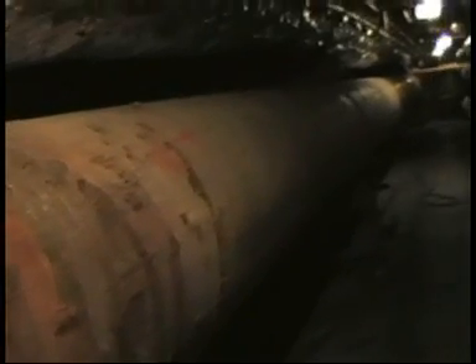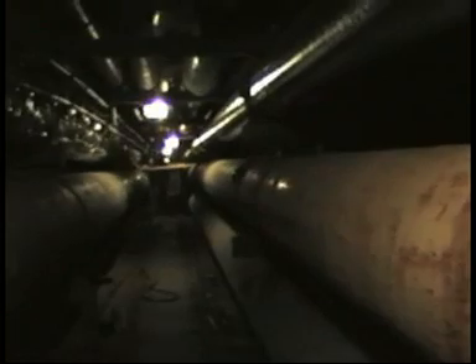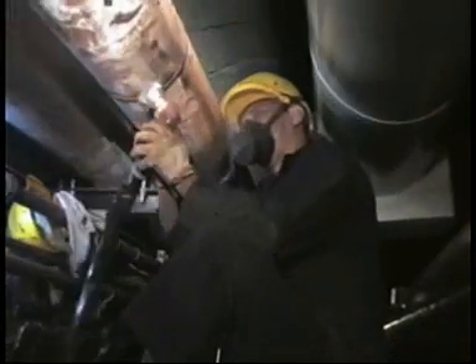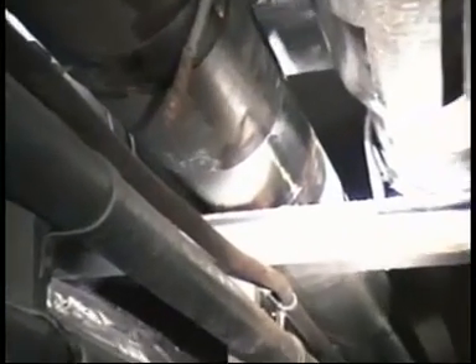As the paint systems were ineffective and the environment such that cleaning and repainting was dangerous and expensive, it was decided to use zinc tape. First was the cleaning using a mechanical wire brush. Then the Isozin zinc tape was applied to the pipe supports and weld areas. The wrapping machine was used on the longer sections of pipe and the magnetic roller on the more awkward areas.